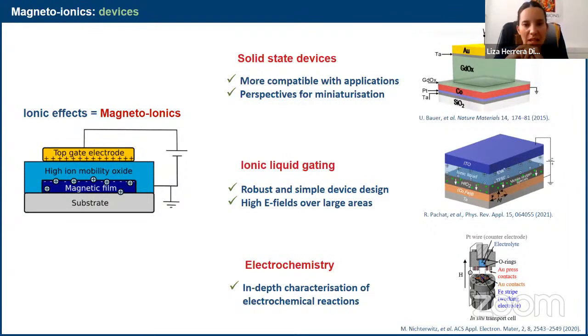The advantage is that although the ionic liquid itself is pretty thick, what you care about when you calculate your electric field is the distance between this layer of ions and your surface, and that can be very small. It's typically considered to be 1 nanometer for each one of the plates, so the effective distance is considered to be 2 nanometers.